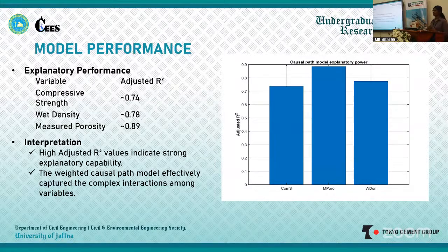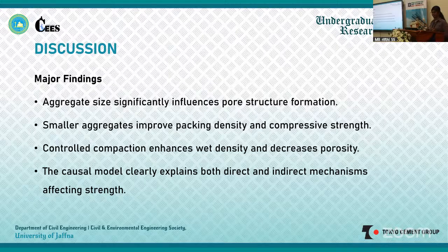Overall, the study demonstrated that the aggregate size significantly influenced the pore structure formation. The smaller aggregates improve the packing density and the compressive strength. The controlled compaction enhanced the wet density and decreased the excessive porosity.